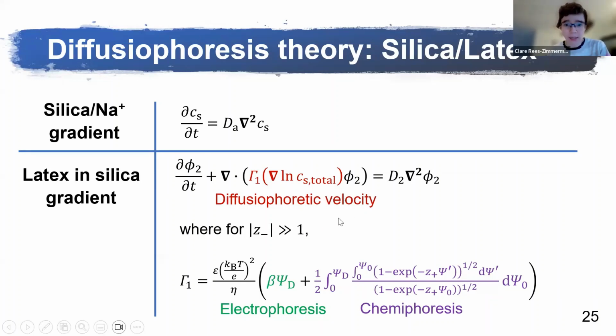That leads us to the remaining term, the diffusophoretic term. We see that this is driven by a diffusophoretic velocity, which is highlighted in red. We have a coefficient gamma 1, our diffusophoretic drift coefficient, and that's in front of the grad of the log of the total salt concentration. For gamma, in the limit where we have many charges on each silica nanoparticle, we can write this equation, and we see there's a combination of contributions from electrophoresis and from chemiphoresis.